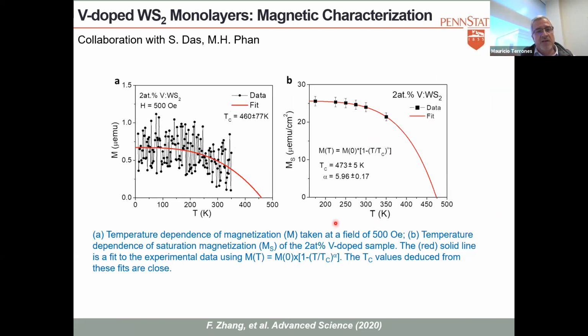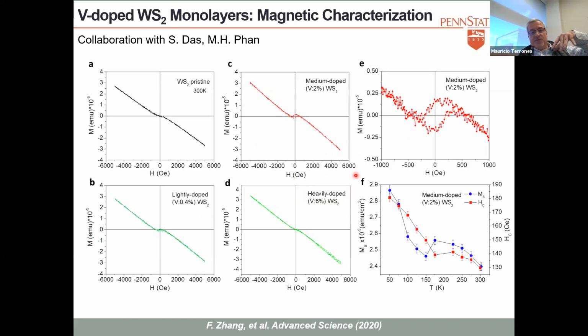So the other thing that we see here is that, well, this is the calculation or extrapolation of the Curie temperature. So we estimated that it was around 400. So it was above room temperature. If you see the magnetic coercive fields at room temperature, they were around 130 oersteds, and at low temperatures they were higher, 180.